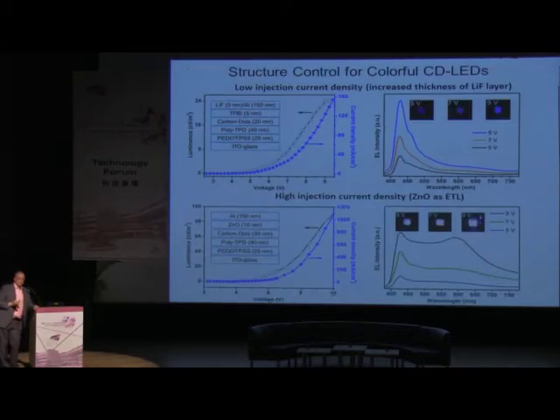And we were sure that it works like that because when we made some other configurations of devices, for example, here we increased the thickness of this electrode over which we inject electrons, and this leads to lower injection current density. So for that device, we could only get blue color. If we, on the other hand, improve injection current density by using this additional zinc oxide layer, which is a very good electron conductor, then we achieve devices which emit only white light. So we can control emission color here on purpose by varying parameters of these devices.